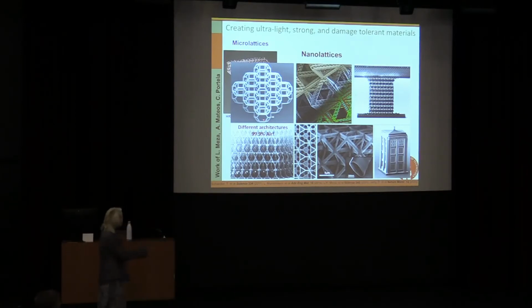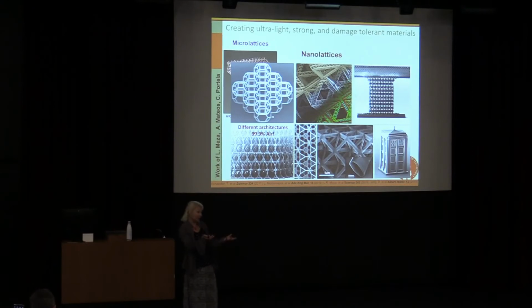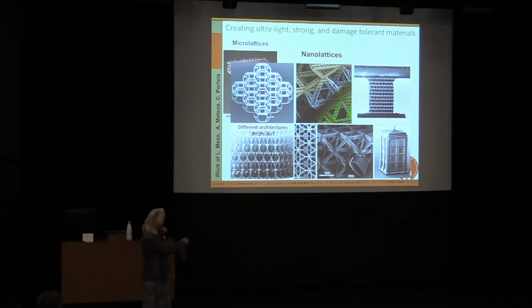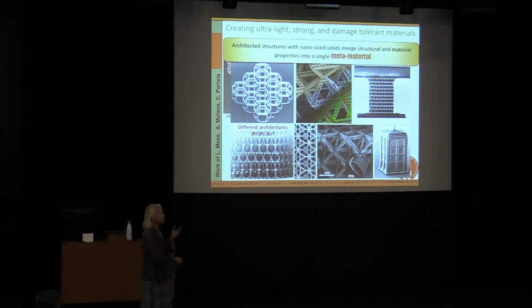Now, when you look at the lattices, the obvious part that comes out is that they're cellular solids. So they're very porous, right? So very, very lightweight. But the less obvious part that may not emerge right away is that the tubes that comprise these woven architectures are hollow. And so we're effectively constructing 3-dimensional interwoven networks of straws, very, very thin-walled cylinders, and the wall thickness here could be on the order of 5 to 10 nanometers. So this single material embodies every length scale from some nanometers, just maybe 5 or 10, to hundreds of nanometers, to microns, which is the dimensions of the unit cell, to hundreds of microns, the dimensions of millimeters and centimeters.